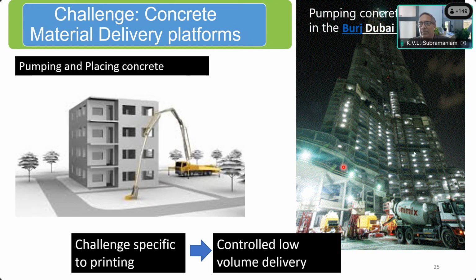I'll give you one example. Burj Khalifa is about 850 meters tall, right? It's almost a kilometer in the sky. In this structure, concrete was pumped to a height of 600 meters. Now, if we just wrap our head around it, concrete was pumped to a height of more than half a kilometer. Now you can imagine the kind of pressure that would be required to lift water to that height. They were able to lift concrete to that height, and concrete is 2.5 times denser.